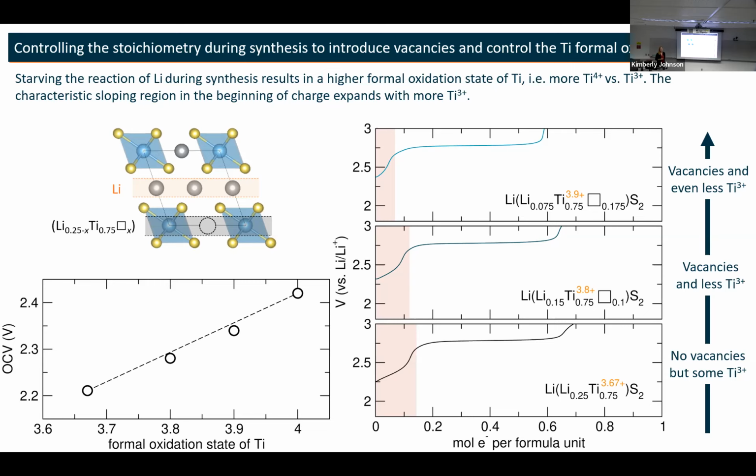And then just one follow-up. So is the high level message that I should take away that if I want to have redox activity in anions, having cation vacancies is helpful? Yes, absolutely. So the high level message is anion oxidation in a sulfide leads to new bonds, sulfur-sulfur bonds. In order to form those bonds, you need vacancies. And that was the cartoon where you had the cation missing and the two sulfurs tilted together. Yep. Got it.